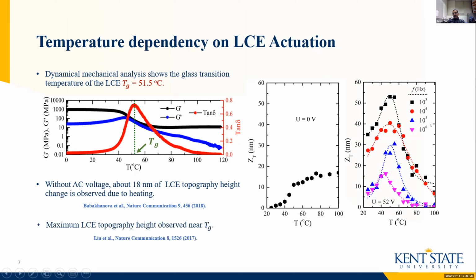Now, if we apply an electric field and do temperature variation at various frequencies, we see that the response of the liquid crystal elastomer increases with temperature and takes a peak, then goes down with further increase in temperature. These peaks correspond to the glass transition temperature we observed via dynamical mechanical analysis. An interesting feature in this plot is the frequency response. Near the glass transition temperature, 50 degrees Celsius, the response at lower frequency, like 1 kilohertz, is higher than the response at higher frequency, like 1 megahertz.